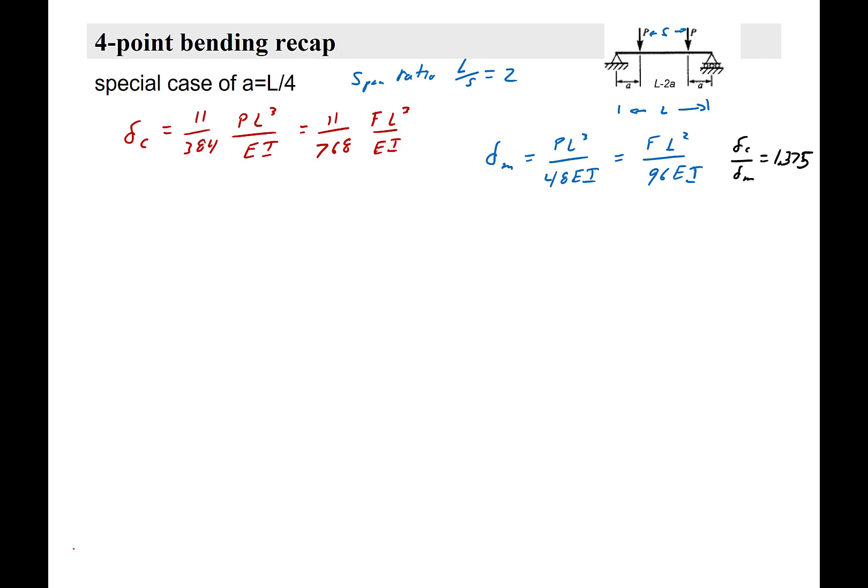In other words, if you get a displacement del M, you can calculate what del C would be by multiplying times 1.375, and you can reconstruct what the center displacement should have been, or at least approximate it, theoretically.